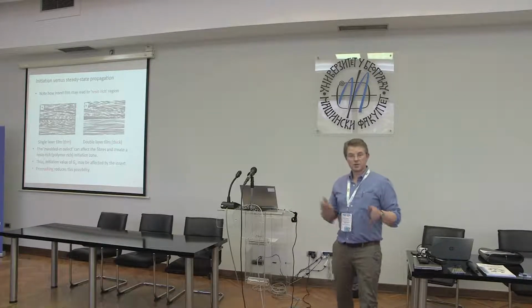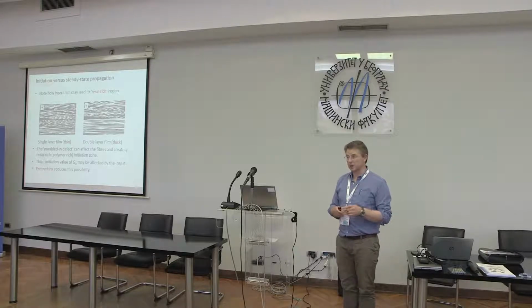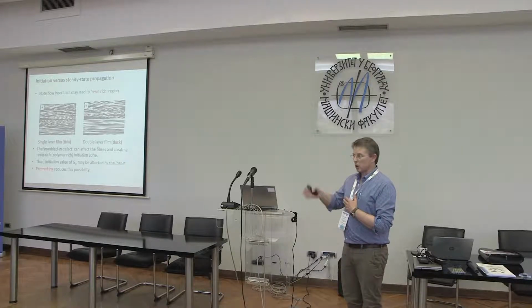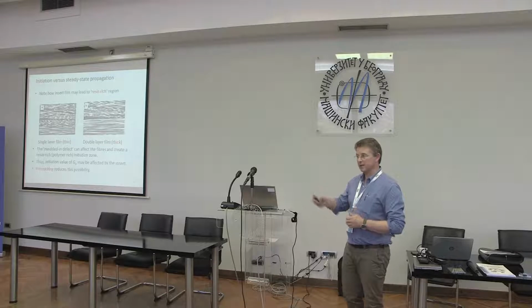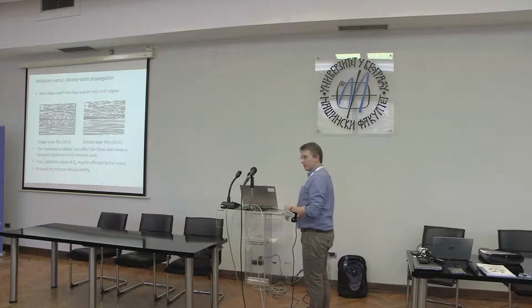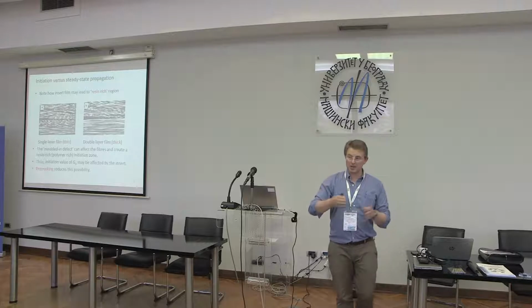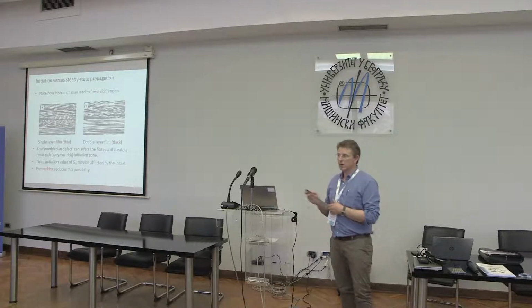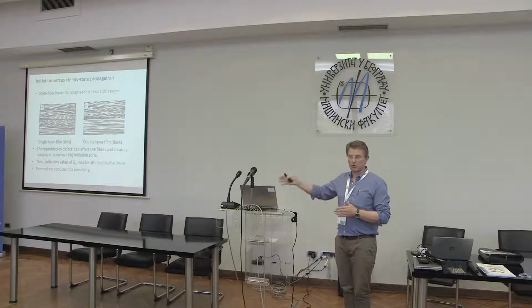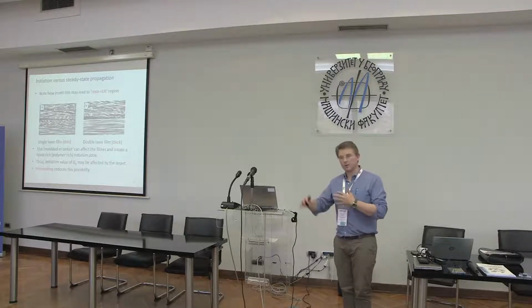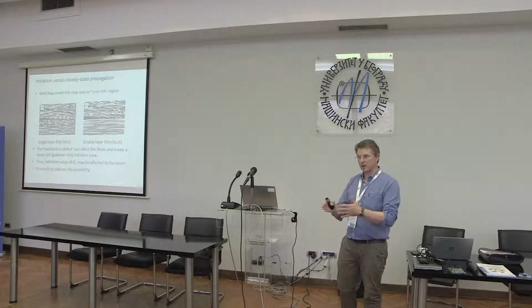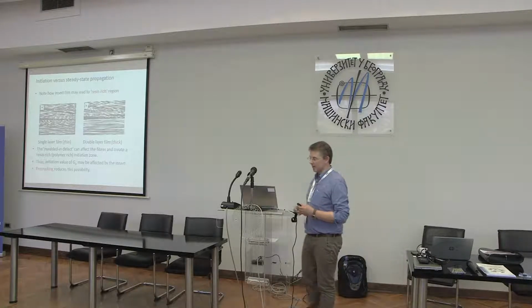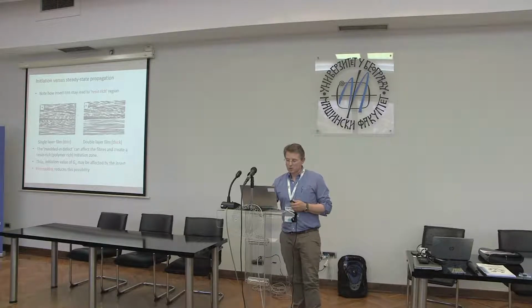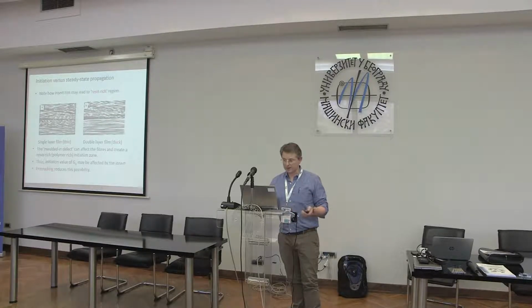So you can, of course, control the thickness, but the other thing you can do is pre-crack. Into the standard methodology, we put in the clause that you have to grow the crack ahead of the film that you embed. So you have a pre-cracking step, and then you unload, and then you reload from your pre-crack. So if you had a situation where your film was too thick for whatever reason, then you would have a way of having grown a more natural crack away from that embedded defect. So that was, if you like, a belt and braces approach built into the standard to try and avoid that problem.